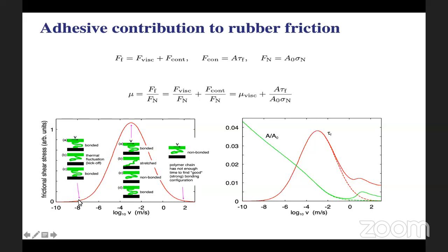So at low velocities, what happens? There is a lot of time for the rubber molecules to bind to the surface, and the frictional shear stress, or the adhesive contribution to friction, is less, because the rubber is binding tightly to the substrate. But you will see a bit of energy dissipation because of thermal fluctuations of order kT, which can break the bonds. At low velocities, you will have a low adhesive contribution.